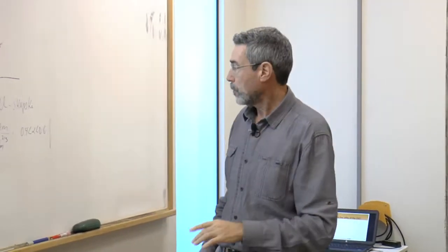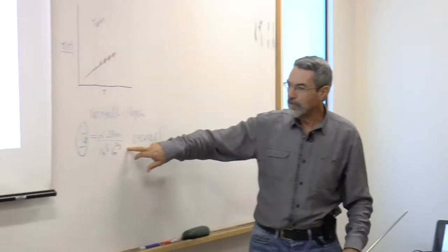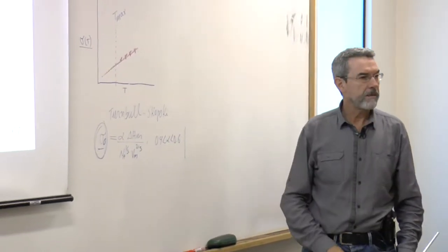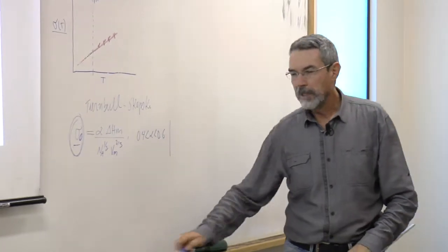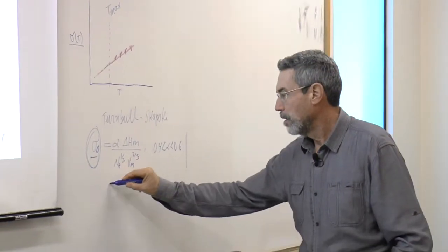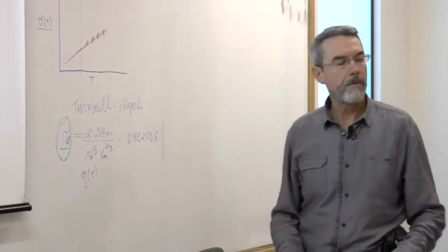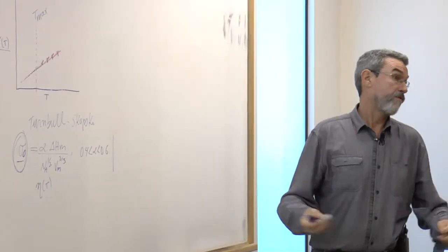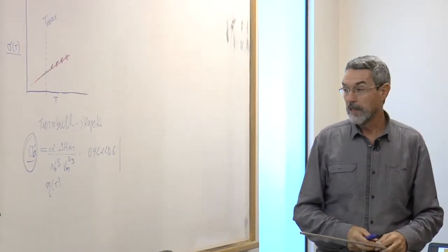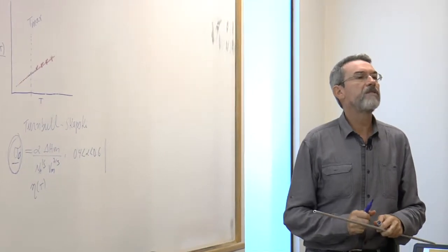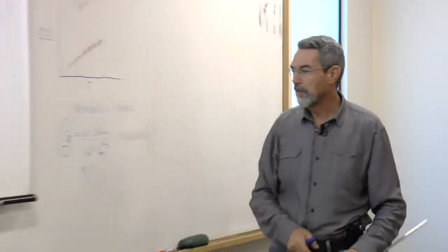Okay, what's the state of the art then? One can use an estimate for sigma for any system. One can use the viscosity, because viscosity is a property that can be measured for any glass-forming system, at least. If the system crystallizes extremely fast, then you cannot measure the viscosity because it crystallizes before you measure. But for any decent glass-forming system, you can measure the viscosity.